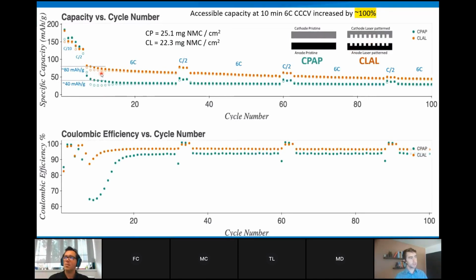Now, because it's so thick, we still didn't expect, obviously, full lithiation or full utilization of the material, but we did see a substantial improvement in how much capacity we can get into the electrode in about 10 minutes. In fact, that improvement that we've observed through multiple repeat tests was on the order of about 100%. So about 40 milliamp hours per gram to about 80 milliamp hours per gram. And the life of the cell also is extended.